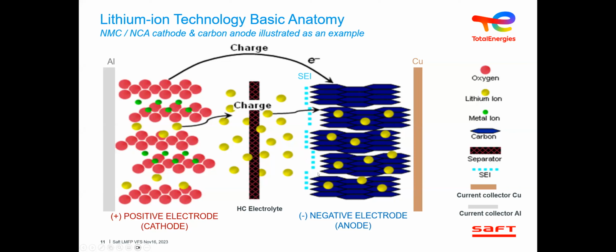The solid electrolyte interface, or SEI, is a very important component of the chemistry, partly using some of the lithium. This is basically capturing and making lithium no longer available, and it's essentially passivating the carbon anode. And this is one of the mechanisms of silicon technology, where the anode fractures, the silicon SEI phase gets recreated and consumes more and more lithium, which makes you lose your capacity. So that's one of the difficulties of these. And the LTO technology, the lithium titanate, does not have this SEI, and that's one of the reasons why you can have very fast recharge, and you can obtain this very high cycling ability and very stable and very strong safety, if that SEI is not there to be compromised and at risk.